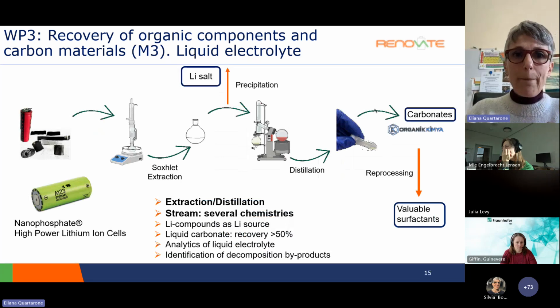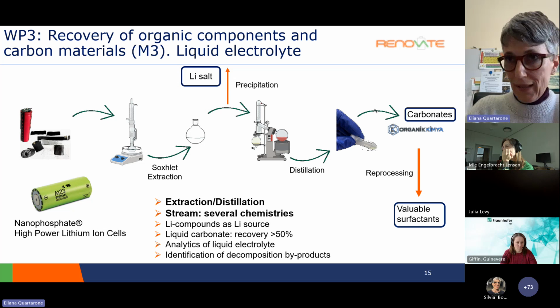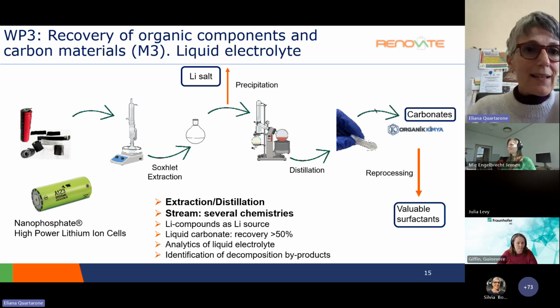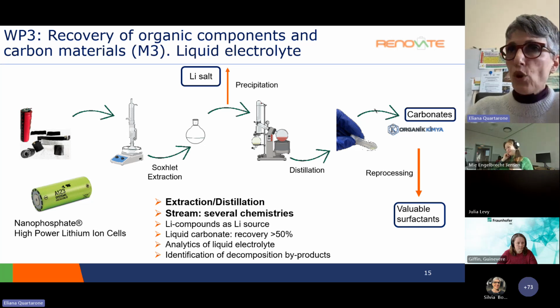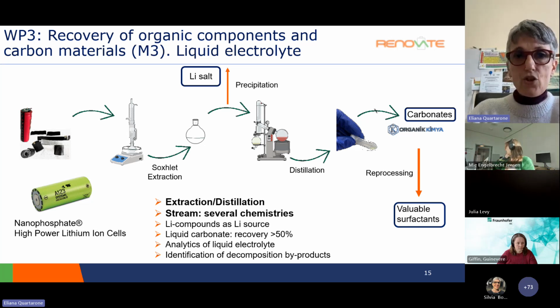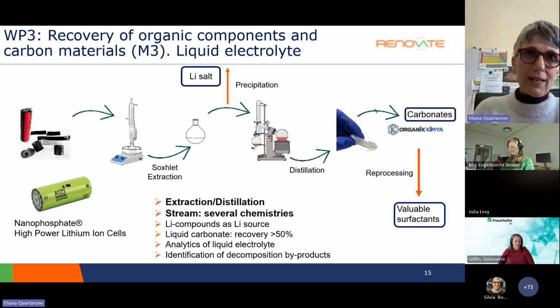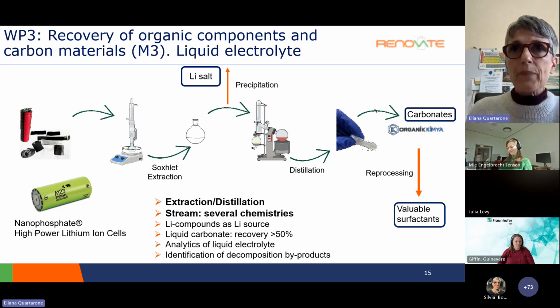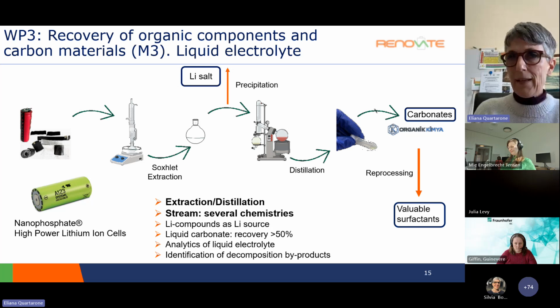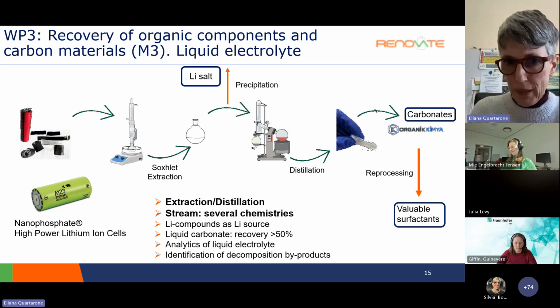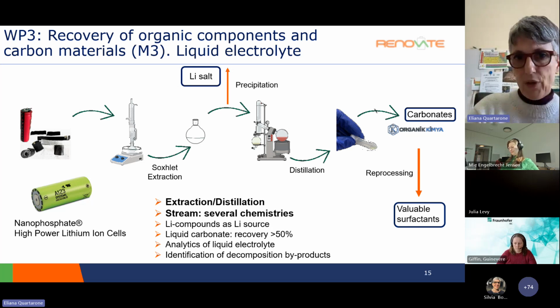And we are extracting the electrolyte by means of Soxhlet extraction, precipitating the lithium salts, and also characterizing it, and purifying the solvents, the carbonates, by means of a distillation approach, and checking by analytics if the carbonates may be reused in a battery remanufacturing process, or eventually, in case of low quality, retransformed into more added value materials, like, for example, valuable surfactants.